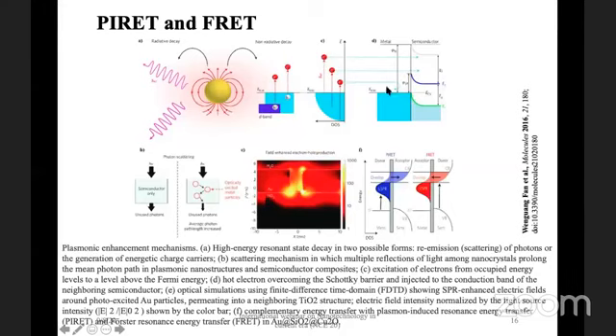We form a Schottky junction over here. So this is a metal and this is a semiconductor. This is the conduction band of the semiconductor. So this electron, when it goes to the higher level, it will go into the conduction band of the semiconductor. So it will transfer its energy into the semiconductor. Once this happens, the process is known as PIRET, which is plasmon-induced resonance energy transfer. And if we have the other way around, we have an electron which is excited in the semiconductor, goes into the higher level, it goes into the metal and excites the plasmon. If the process is reversed, then we have the FRET process happening in these nanostructures.